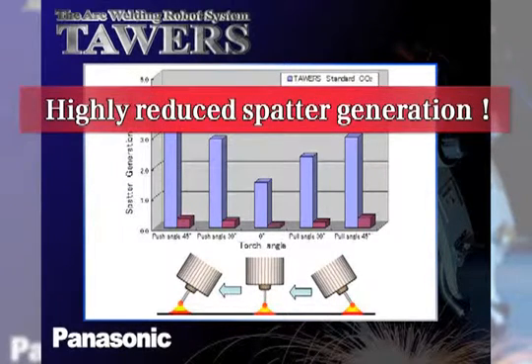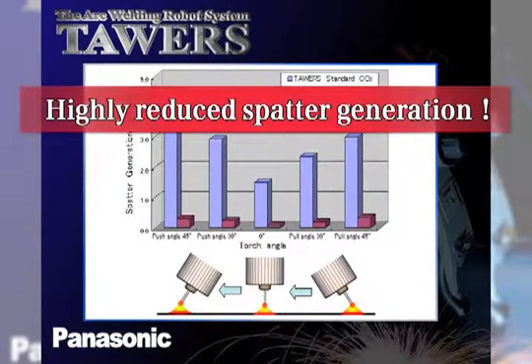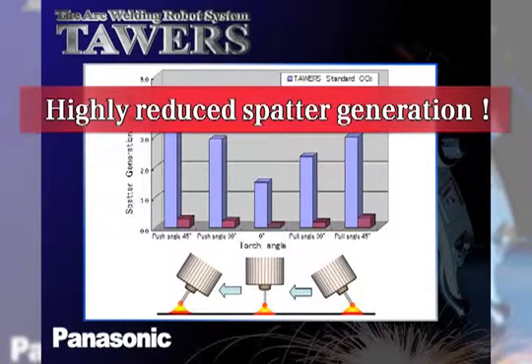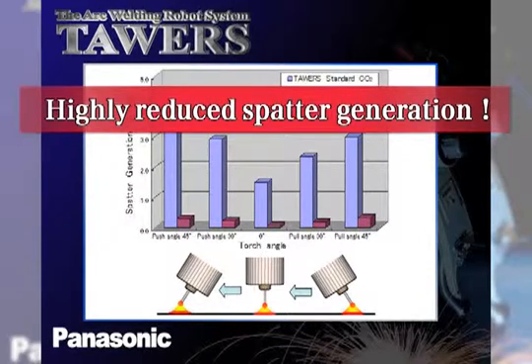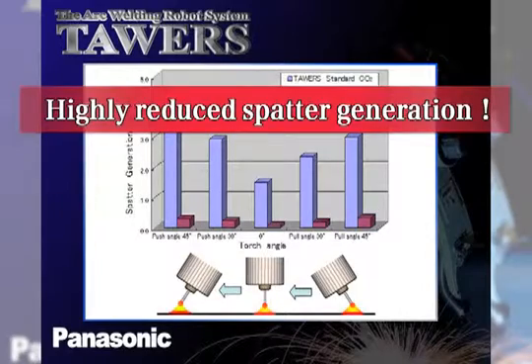In conventional welding processes, when the torch angle — drag or push — exceeds a desirable amount, typically plus or minus 10 degrees, the spatter level and welding process run out of control. As you can see from the spatter generation chart, the active wire feed process has an excellent effect on spatter generation performance since it is not affected by arc reaction forces.